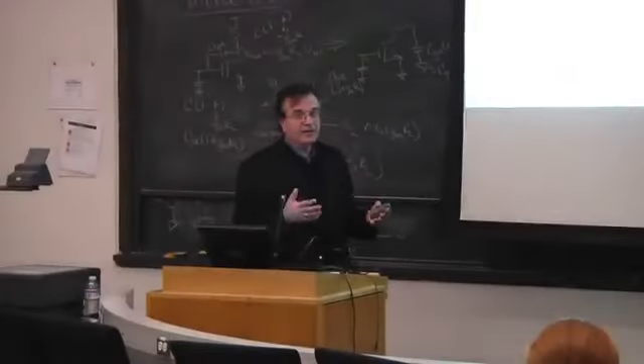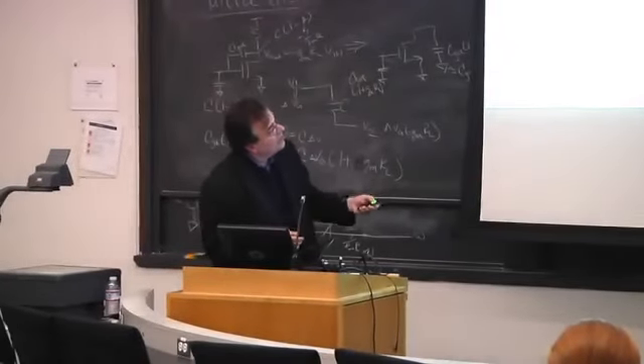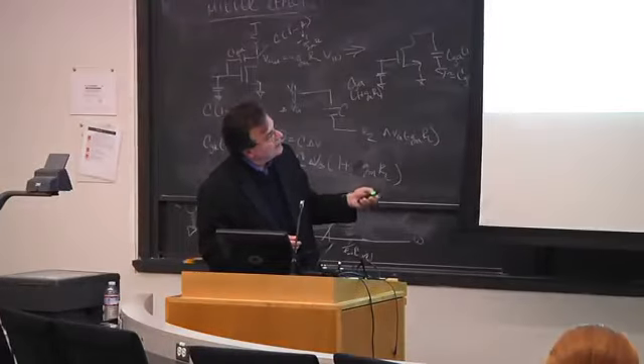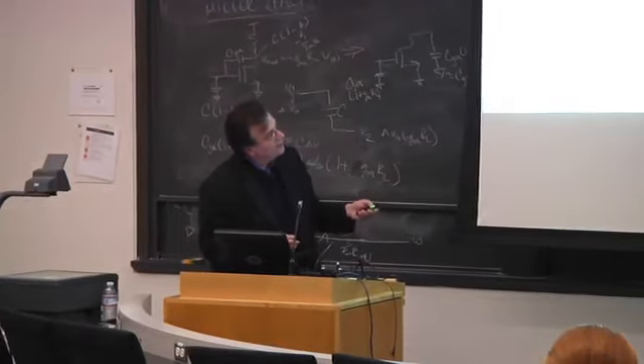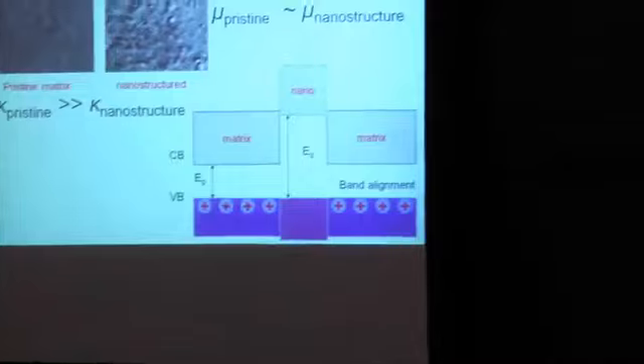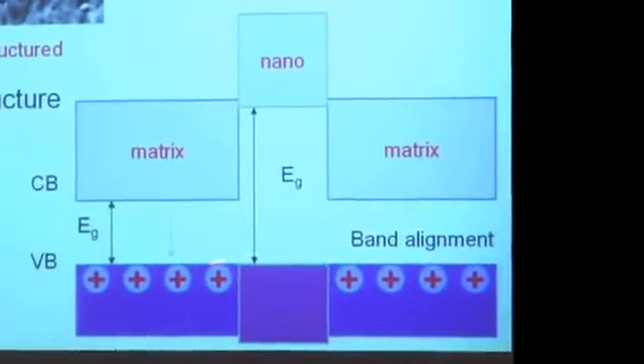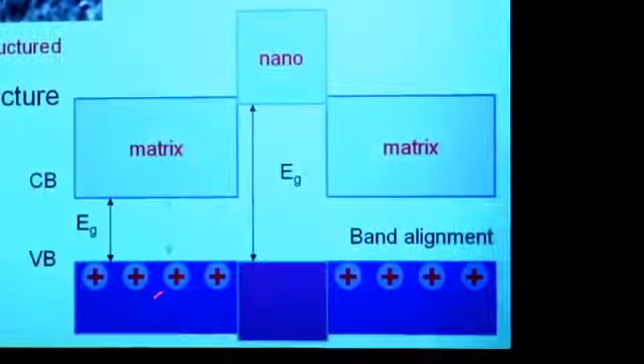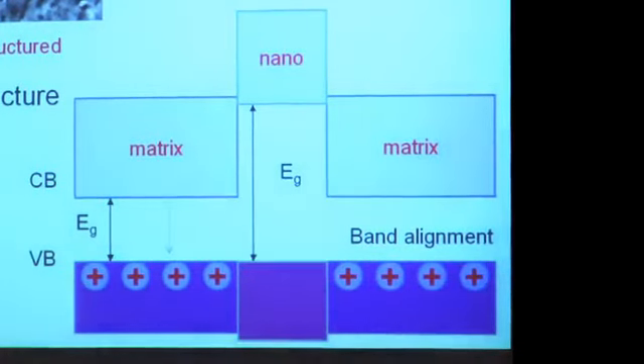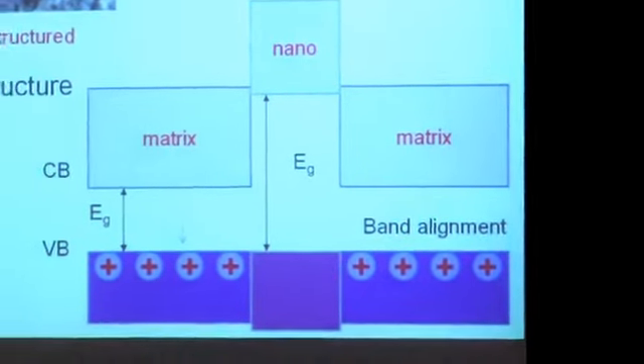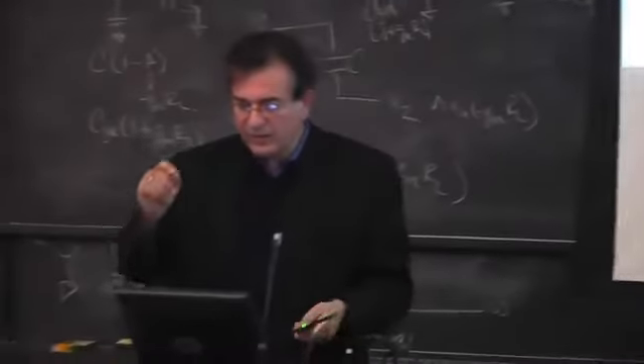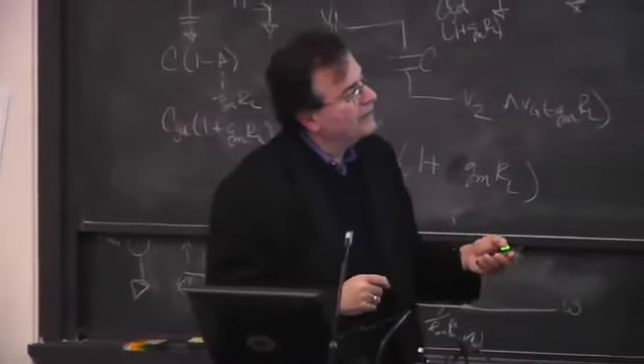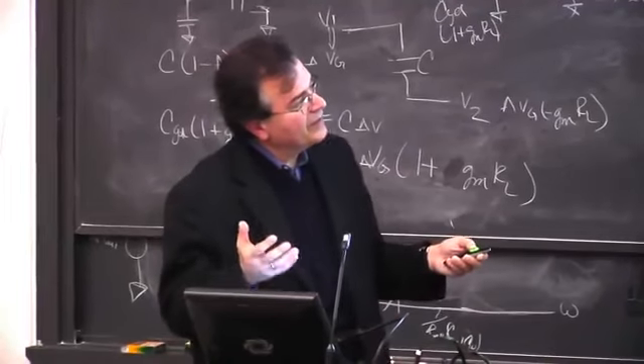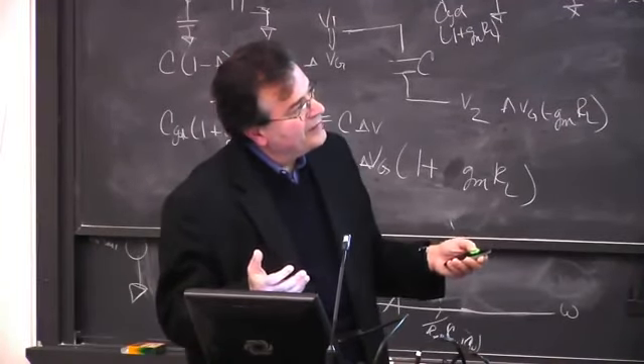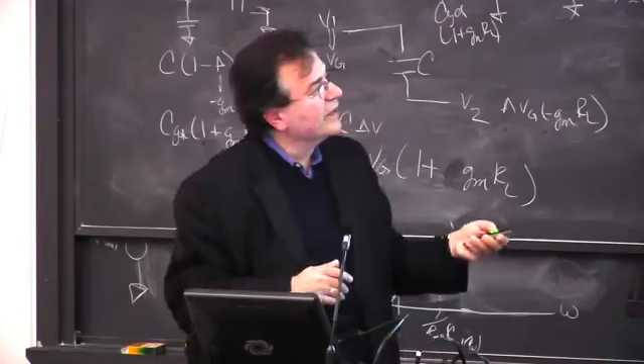Both are tellurides. Strontium telluride is a wide gap material, and the matrix is a narrow gap material. But both have, in their valence bands, tellurium-based orbitals. So the energies at the band extrema, the valence band extrema, are more or less the same. Calculations indicate at 0 Kelvin a band offset of 0.15 eV. But with thermal broadening, by the time you get to room temperature and above, these things more or less become equal in energy.